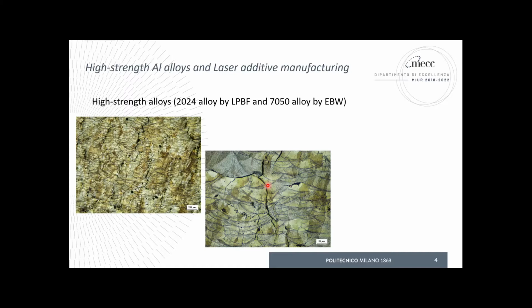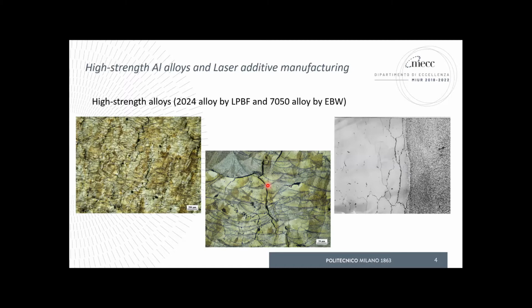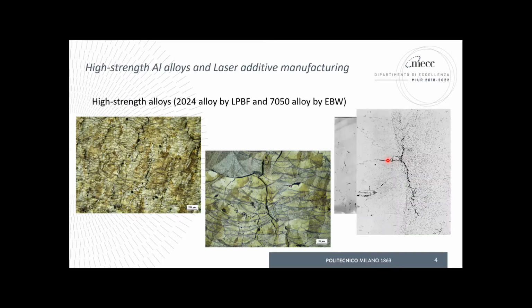This kind of concern is nothing new, actually. I brought out from my very old files some micrographs of the microstructure generated during welding of 7050 alloys. It's from lots of years ago, but the problem was always the same. Again, here we got hot cracks at the grain boundary of the heat affected zone, but also in the weld metal zone. So nothing new. But of course, we have to consider laser additive manufacturing as a kind of mini welding operation, which is repeated lots of times to produce a 3D part. So we can rely on the experience and expertise we have in welding.